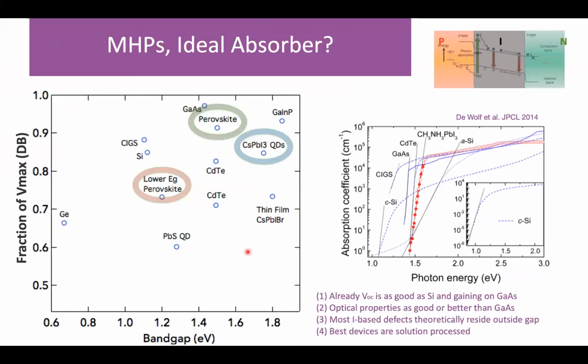The other thing you obviously have to have is a strong interaction with light. This is some work by DeWolf et al. early on that shows that you clearly have really, really strong absorption for these materials. You also have this fraction of the detailed balance voltage maximum, right? So you can imagine that in the context of this band diagram, the maximum voltage you could extract would be equal to your electronic gap. So if you have a value of 1 here, that's to say that the voltage that you produce is maximum based upon the detailed balance limit for the band gap that you have.